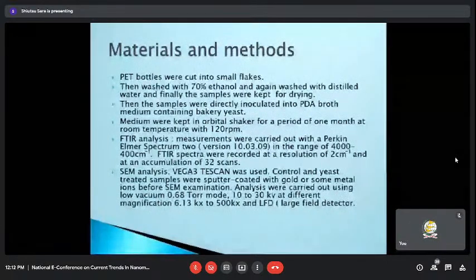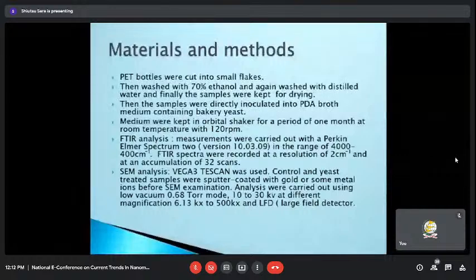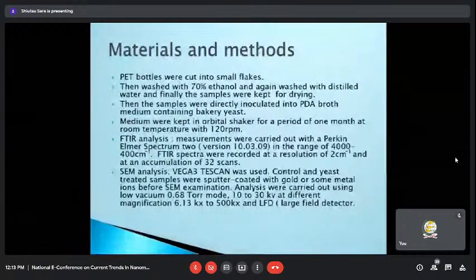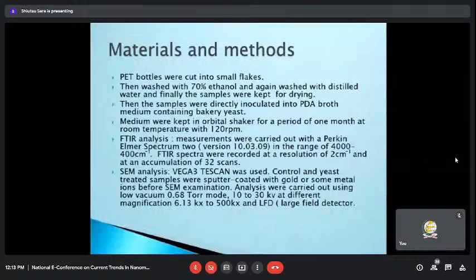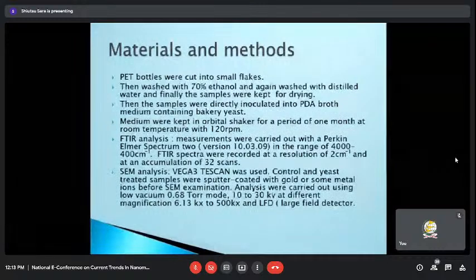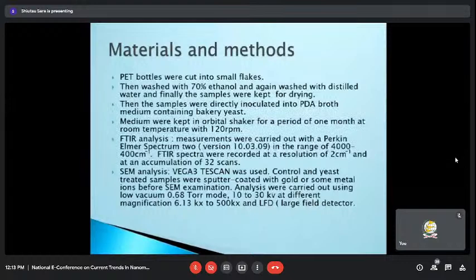After drying, some samples were directly inoculated into a PDA broth medium containing the bakery yeast. Some were directly inoculated into that medium, and some were kept untreated for a period of about 1 month. After 1 month, those two samples were sent for FTIR and SEM analysis. For FTIR analysis, measurements were carried out with a Perkin-Elmer Spectrum 2, and spectra were recorded at a resolution of 2 per centimeter. For SEM analysis, a VEGA3 TESCAN was used, and analysis was carried out using low vacuum 0.68 Torr mode at different magnification levels.